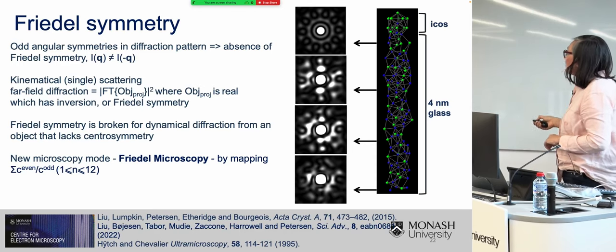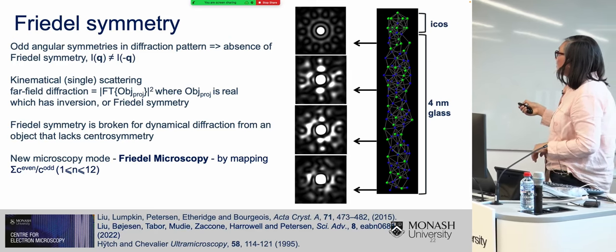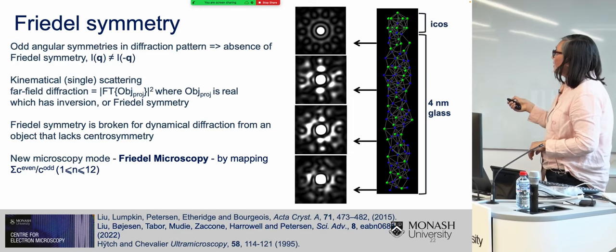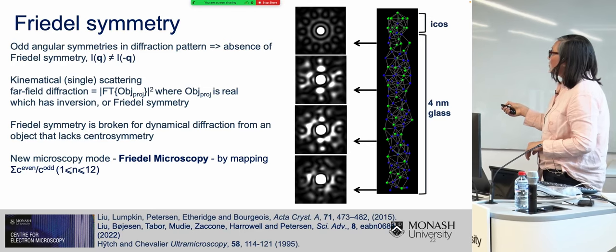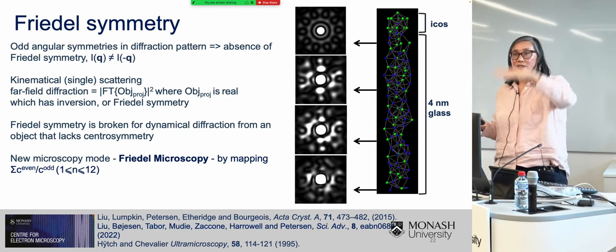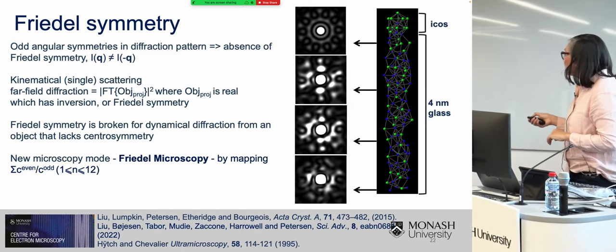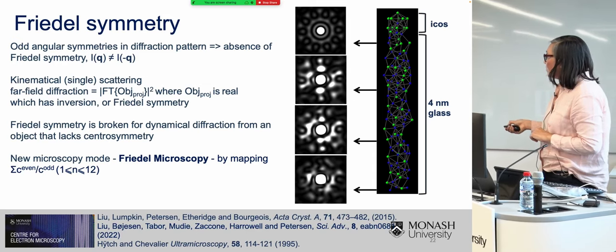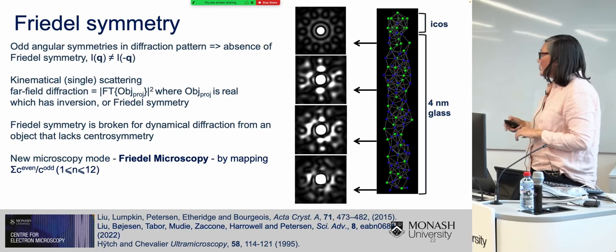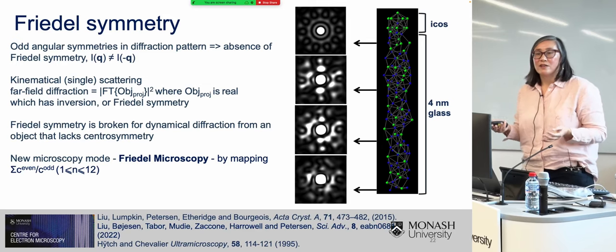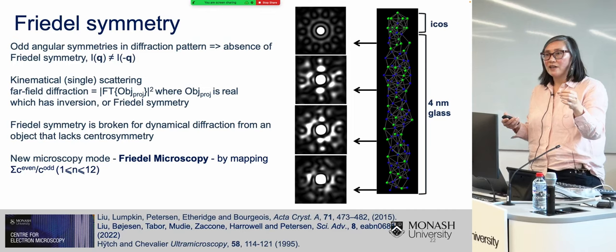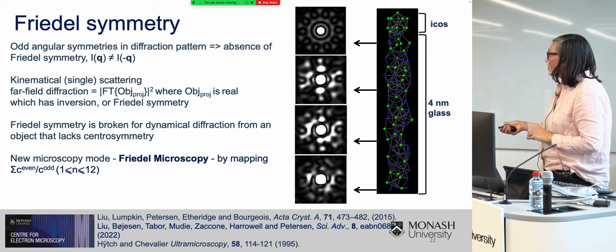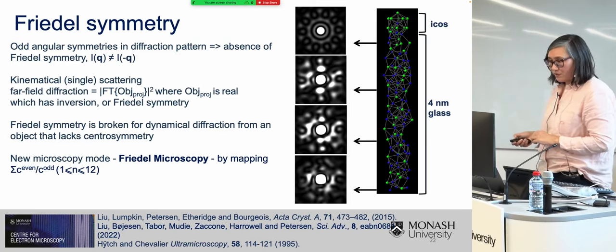So here you can see an example using electron nanodiffraction, where if I make my output wave from my focused probe here, then we have a high degree of centrosymmetry or Friedel symmetry in the diffraction pattern. As the wave propagates through the material and undergoes dynamical diffraction from interacting with the material at different depths, then you can see that the diffraction pattern actually breaks inversion symmetry. And so these observations led me to propose that I could measure an interesting parameter related to the local centrosymmetry in a glass just by mapping out the breakdown of the Friedel symmetry in my diffraction patterns. So the ratio of the even Fourier coefficients to the odd Fourier coefficients.